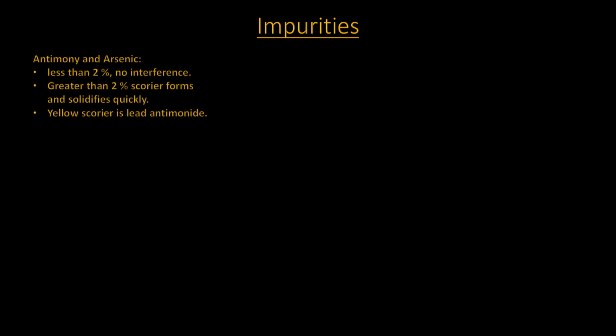You will encounter impurities. Some will interfere with the cupellation. Some are hard to eliminate as oxides. Loss of gold and silver is inevitable. Any antimony or arsenic, less than 2% in the bead, will not interfere with the cupellation process. However, greater amounts will form a scoria and solidify over your bead and will expand. This can even split the cupel.